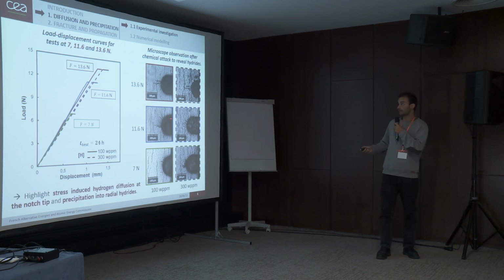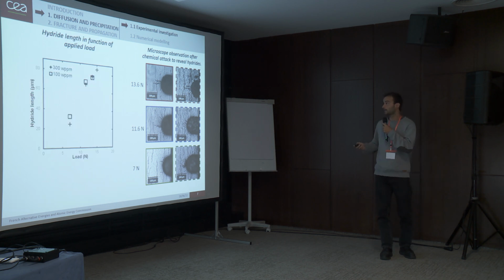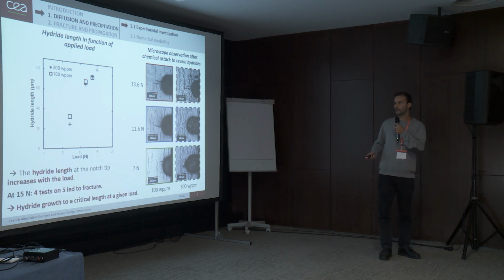The first one is the increase of hydride concentration at the notch tip. That highlights the stress-induced hydrogen diffusion at the notch tip and the precipitation into radial hydrides. And if you look at the length of the hydride at the notch tip, shown on this figure, you can see that the hydride length increases with the load. At 15 Newton, 4 tests out of 5 led to fracture. So the hydride grows to a critical length at a given load.